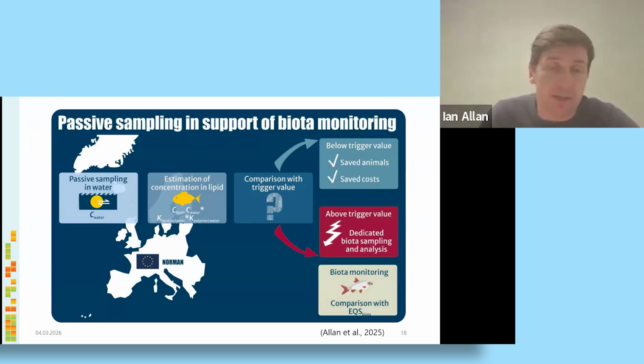And that's sort of the procedure we're proposing. Annika Janke made this very nice picture. So passive sampling in water, we estimate the concentration in lipids. We have a trigger value, whether that's an EQS or a value according to the EQS. If we pass that trigger value, then we have to implement dedicated biota sampling and analysis. But if we're below or well below that trigger value, then we don't have to do biota sampling. So that's at least one way we think that passive samplers for such substances could be used.